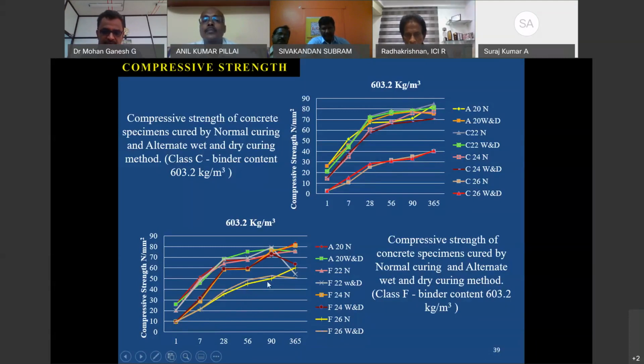Only a nominal or marginal difference is there between both mixes due to strict water cement ratio with superplasticizers, high range water reducing admixtures. That is Glenium 4 we have adopted, fourth generation superplasticizer. We used it, sir.